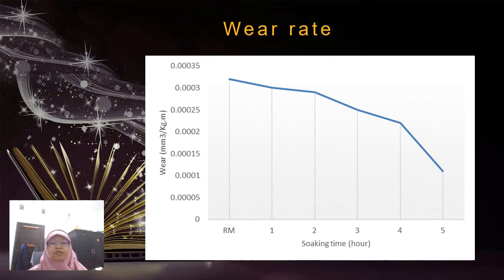The DCT process causes the release of internal stress and the reduction of microstructural defects, which are important factors in increasing the wear resistance and strength of the material. The decrease in the maximum wear rate occurs at 5 hours DCT with a very significant decrease. It can be concluded that the DCT process on FeAl-MnMo alloys increases the wear resistance up to 65%.